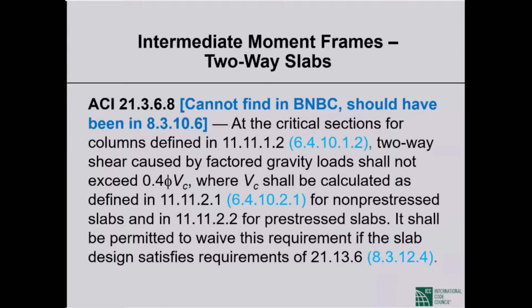So ACI 318 has a very important requirement that says at the critical section for column, this is the critical section for two-way shear that you are very likely familiar with. I have thrown in a few slides. We will go over that. So at the critical section for two-way shear, shear caused by gravity loads shall not exceed 40% of the shear that concrete alone can carry. V sub C is the punching shear capacity of concrete, 4 square root of F sub C prime in our units. Phi is 0.75. So 4 times 0.75 is 3 square root of F sub C prime. We are saying that the punching shear due to gravity shall not exceed 40% of that, and that will leave enough room for additional punching shear caused by earthquakes to be resisted by the slab without the help of any reinforcement.